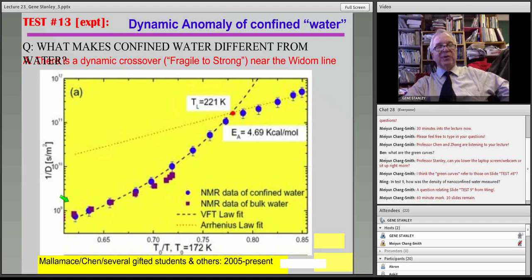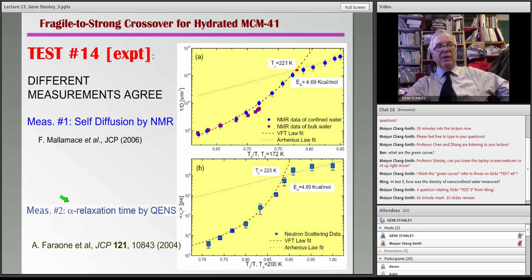Now let's look at the similar data, only this time from MIT, the group of Chen. Sorry, this slide is small. If you're not using your full screen, this is a good chance to use the full screen. And you see here on the top half, you see just a repeat of what you just saw, the Mallamace experiments of Mallamace's group on self-diffusion. And here on the bottom half, you have a different experiment, not measuring self-diffusion, but measuring the alpha relaxation, not by NMR, but by quasi-elastic neutron scattering. So totally different experiment, measuring a totally different thing, but you see exactly the same phenomenon, a fragile liquid crossing over to a strong liquid, and moreover, the crossover point is exactly the same temperature, this magic 225, or as I like to call it, the Widom temperature.